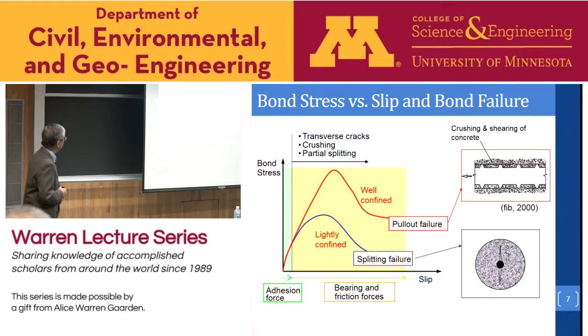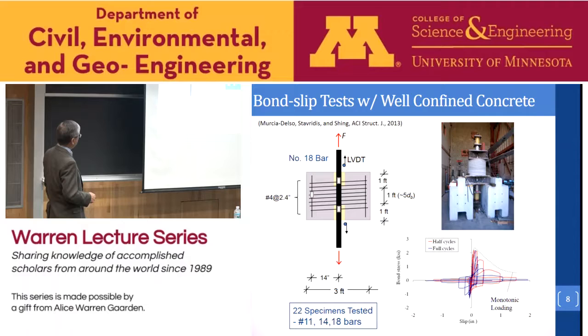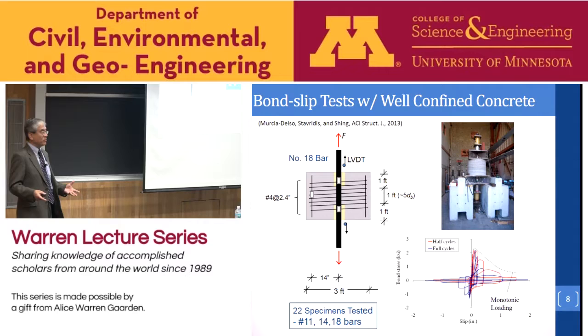So to characterize the bond slip behavior of large diameter bars, we did 22 tests on number 11, 14, and 18 bars. Okay, so each specimen is like a concrete cylinder with 3 foot in diameter. And then this is the bond length of the bar, and this is just unbonded area to mitigate the stress transferred from the reaction forces into the bond. So this shows a test setup, and we did a number of tests with different load history, like monotonically increasing load, cyclic loading, some fully reversed cycles, and some just cycle in one direction and a little bit in the other direction. So we look at the influence of the load history on the bond slip behavior.